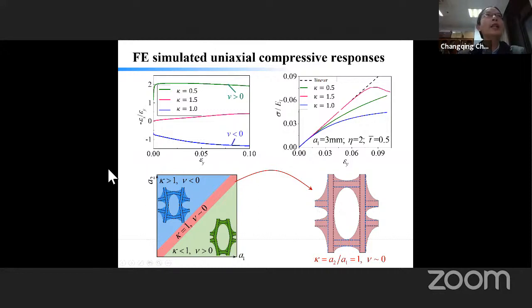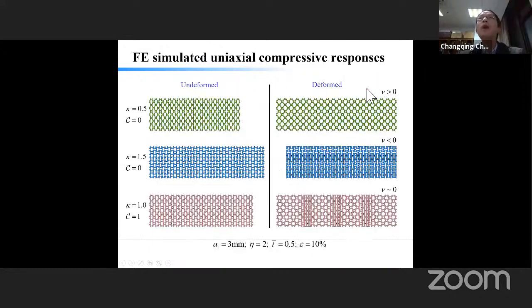Now, if we look at the deformed shape corresponding to the stress point about here, where the strain is about 10%, you will see a very striking phenomenon. For kappa not equal to one, the first two cases, the deformed configuration is uniform. However, for kappa about one, you can see we have a highly localized deformation pattern that is evenly spaced.